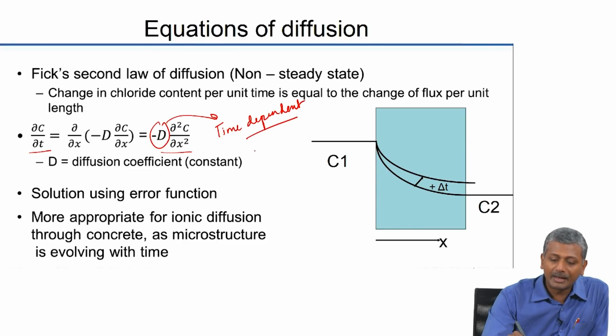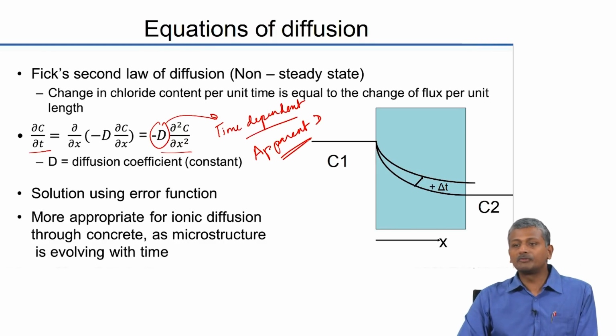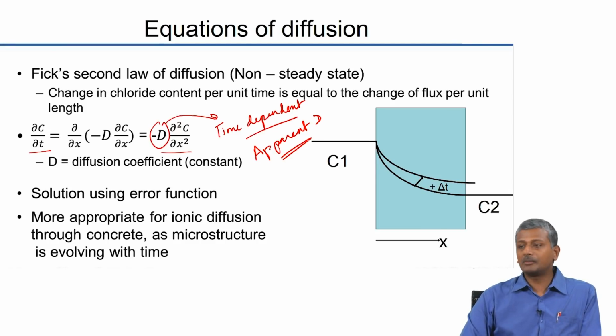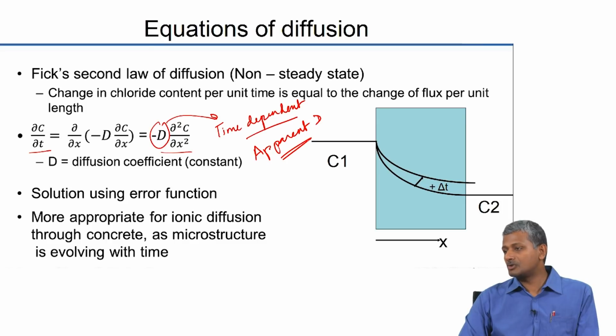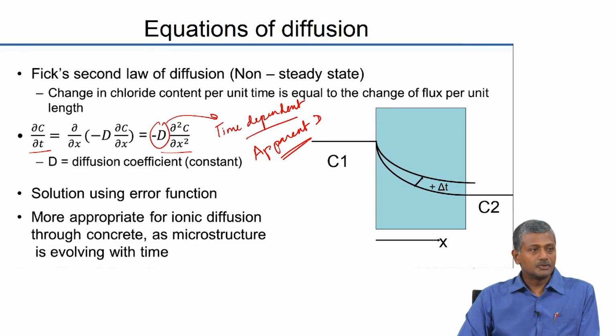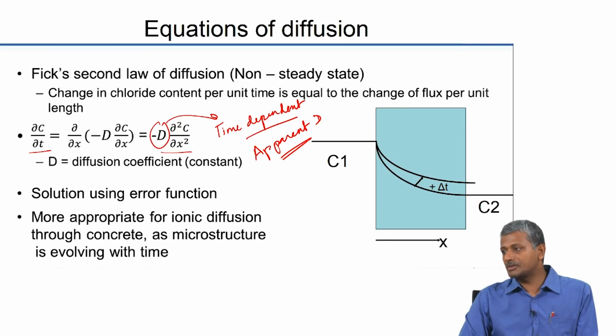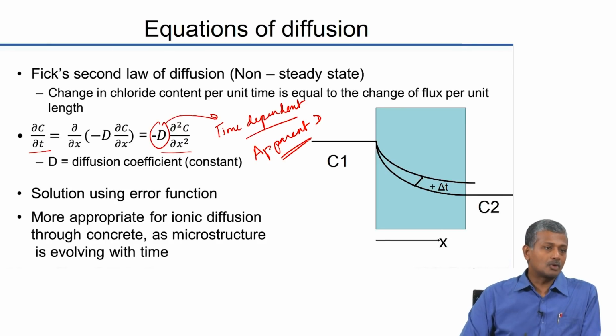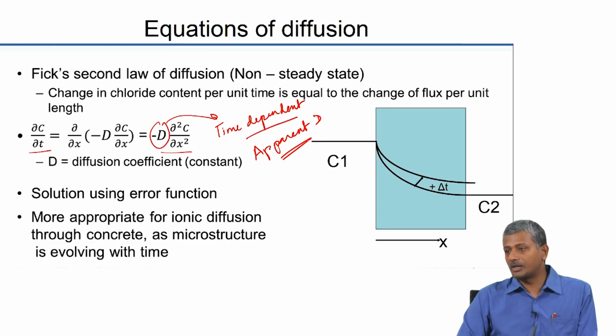That's why we call it an apparent diffusion coefficient. It's not really the true diffusion coefficient, because a true diffusion coefficient will be independent of the time at which you are evaluating it. So this is an apparent diffusion coefficient because it is time dependent, okay. So you need to be careful about your measurement of this diffusion coefficient based on experiments done on concrete. You need to exactly specify the age at which you have determined this value, okay.